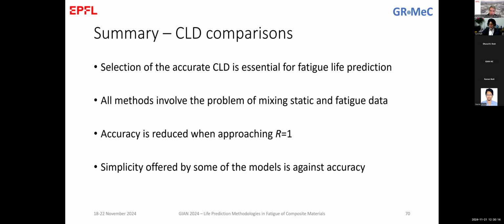So simplicity is offered by some models. You remember we discussed, for example, the Kawai model. It needs only one SN curve, but in a lot of cases this is against the accuracy of the models. The more simple the model, the less accurate it is, or in different words, the simple models are good for specific cases. Kawai developed his models for unidirectional carbon, and in this case it works. But if we take this model and try to apply it, for example, to plus minus 45 glass, then we might see that it does not work well.